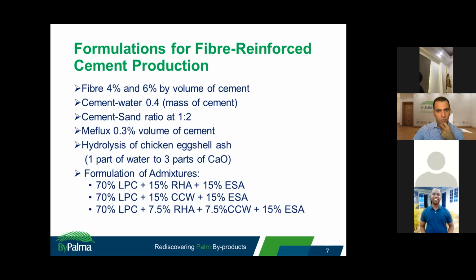The same thing, we use fiber at 4% and 6% by volume of cement, with a cement-water ratio of 0.4 and our cement-sand ratio. Then we introduce something again in the course of this particular experiment: Meflux. What is the function of Meflux? Because at this stage we're already adding two more materials, and we don't want to change the water-cement ratio from 0.4.